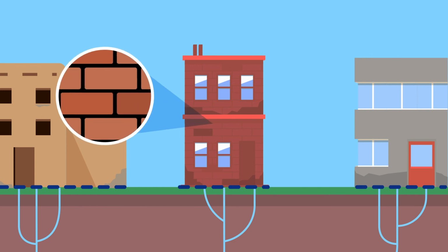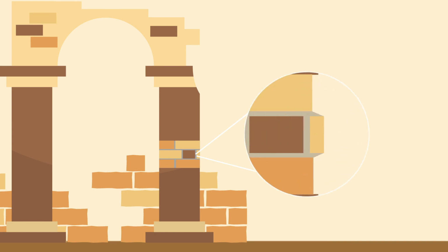Finally, in masonry structures, the properties of the mortar should be optimized in regard to those of the brick and/or stone blocks. Indeed, having a more sorptive mortar will channel water through the mortar rather than through the more valuable masonry elements. This, along with having the mortars being more compliant than those elements, are important parts of conservative measures in historical masonry buildings.